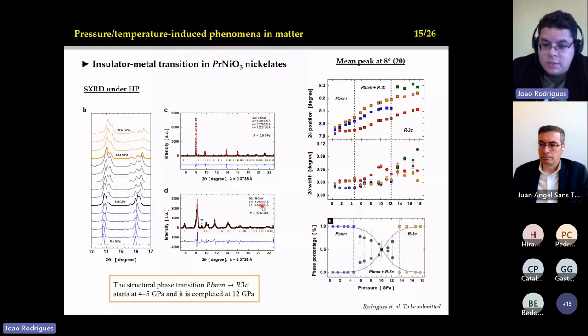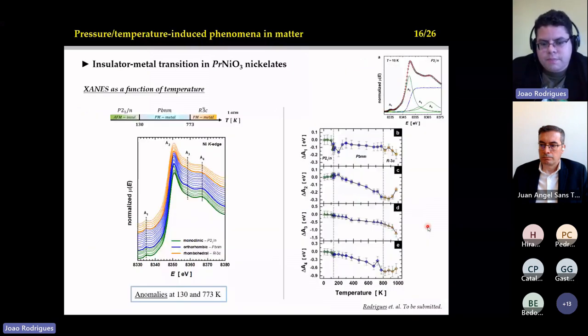Nobody observed this before, and we managed to do it thanks to the very nice spot at the ID27 beamline. Then we continued to explore what is happening with temperature, but now using the near-edge part of the spectrum, and you see here that we map with temperature all these transitions, the two transitions from the insulator to metal and then to the metal.